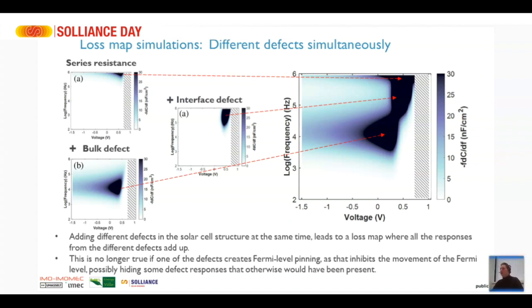If the defect is identified — for example, as an interface defect at the cadmium sulfide/CIGS interface — at least you know what process you have to work on. It won't help much to work on the back contact if the defect is between the CIGS and the cadmium sulfide. In that case I would work on the cadmium sulfide deposition process, do some cleaning after CIGS deposition before cadmium sulfide deposition, or even use a different material like zinc oxy sulfide.